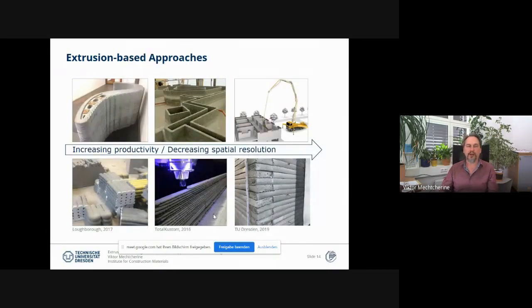We can also try another classification approach, based on the size of the filaments we deposit. In most cases, the approach in the middle is used, where we have filaments that are not very wide, but also not very narrow, which can be used as a load-carrying structure, or, as is frequently the case, as a permanent integrated formwork filled later with concrete or reinforced concrete. If we go to the left, we have the approach introduced at Loughborough University, where thin filaments are placed very close together, forming a kind of monolithic structure. Of course, we have high resolution here, which also enables such openings.